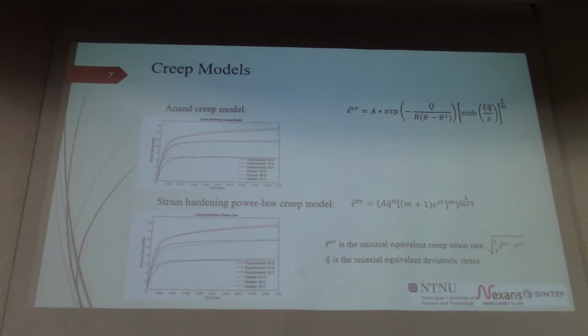As an example, what we want to do is to calibrate the material models and then use them to reproduce the full-scale component behavior. These are two quite well-known creep models that are already available in commercial software. In the case of the Anand creep model, it is fairly complicated. There is quite a big number of parameters that have to be calibrated, but it will give good results in this area, this plateau. This is for a constant strain rate, a constant stress reached, that is a secondary creep region, while the strain hardening power law creep, although it's much simpler, with only 3 parameters to calibrate, is not able to reproduce this part of the behavior.